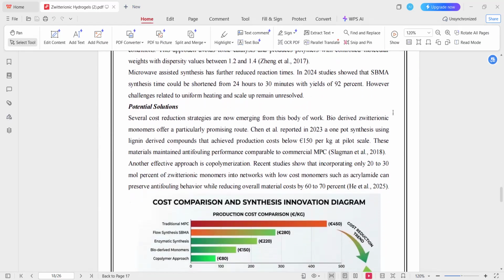Microwave assisted synthesis has also shown great potential. Studies published in 2024 demonstrated that sulfobetaine methacrylate synthesis time could be reduced from 24 hours to just 30 minutes while maintaining yields above 90%. However, challenges related to uniform heating and scale up still need to be addressed before industrial implementation.